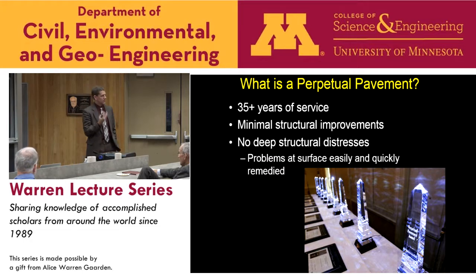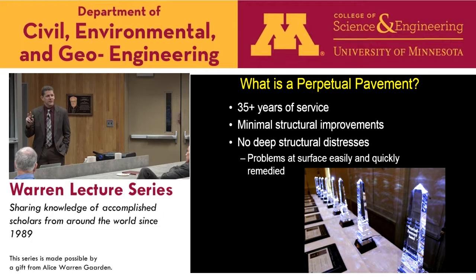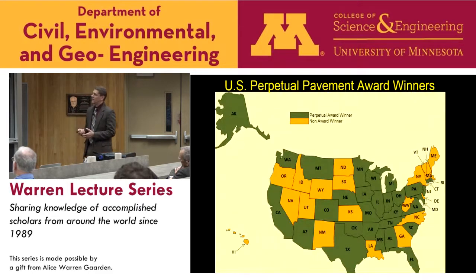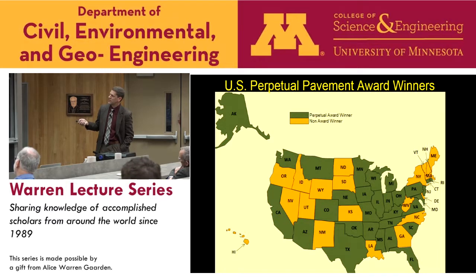So if we don't have deep structural distresses, any problems we see in terms of the wearing surface, or maybe we have a friction problem, maybe the aggregate has started to polish, we can easily and quickly remedy that at the surface of the pavement. And that can be done overnight. Mill up a length of road and put down the new riding surface, and we'd hardly even disrupt the public. These are all award winners. All the green states here, from Alaska to Florida, have every climate. We've identified these kind of roads that have lasted a long time.